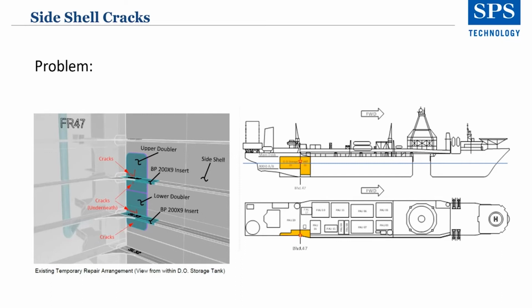So on the left-hand side image, you can see where the transverse bulkhead meets the longitudinal side shell, cracks have formed. The cracks originally appeared at the bulb collar plate weld connection on the aft side of the bulkhead. Backing brackets were fitted during the repair. An existing temporary doubler repair was put in place.